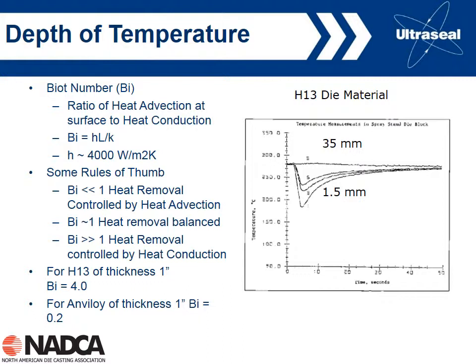What we're looking at here is the temperature of the die versus time for different depths into the die. So 1.5 millimeters is basically adjacent to the surface, versus 35 millimeters. 35 millimeters is just less than an inch and a half. So if we make our casting or spray our die at the surface, 1.5 millimeters, we see a big impact. But 35 millimeters into the die, basically we see no change at all. So there's no change in the die temperature throughout the die casting cycle at only an inch and a half into the die. So we have this kind of transient layer.